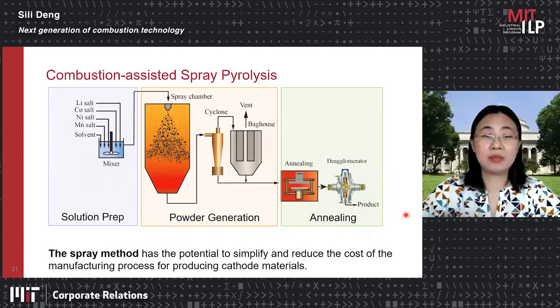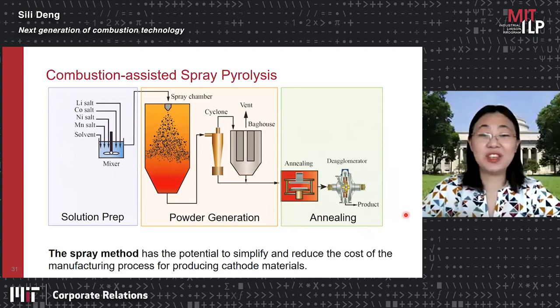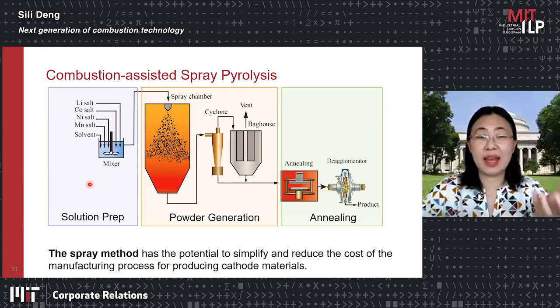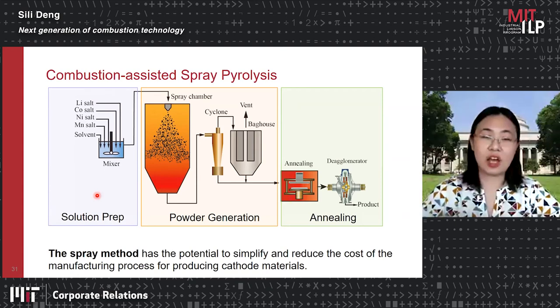And the flame or combustion assisted spray pyrolysis process, from the figure itself, you can see it's relatively simple. Again, you need to have the solution preparation, but here the lithium salt is added and mixed with other types of salt such that you are mixing them in the liquid phase, which in theory should be much more homogeneous than if you mix it in the solid phase.